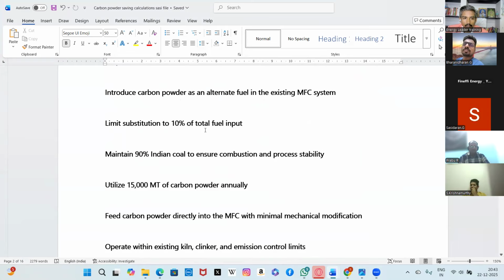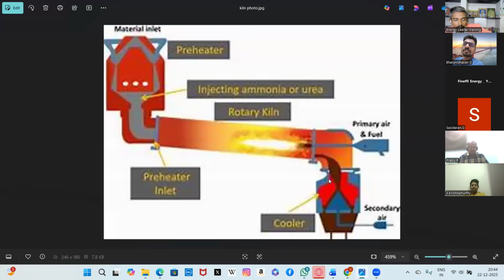As I said, the limitation of the substitution part is 10%. In the fluidization chamber and kiln, both, we use annually nearly 150,000 metric ton of Indian coal, 100%. In the fluidization chamber, we use nearly 70% of the coal, and the remaining 30% of the coal is used in the kiln part, where the clinkerization takes place. There the primary air and the kiln are burning, so that 30% coal is consumed. So the major consumption area is where 70% is.